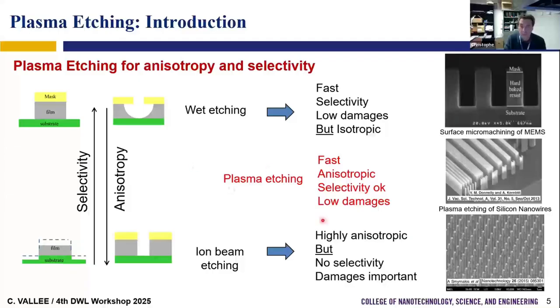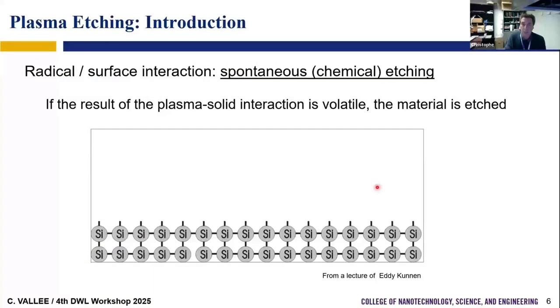This is why plasma etching is very useful, because in a plasma process you have both chemistry with radicals and ions, so you can combine the benefit of wet etching and the benefit of ion etching to have a fast, anisotropic etching with good selectivity. When we do plasma etching, we need to form from a solid a spontaneous volatile byproduct. This is the basis of chemical etching.